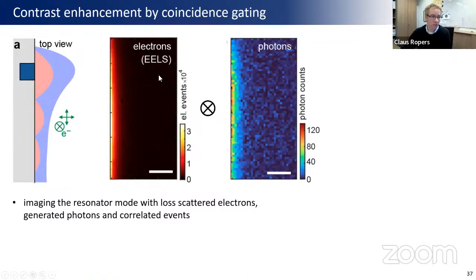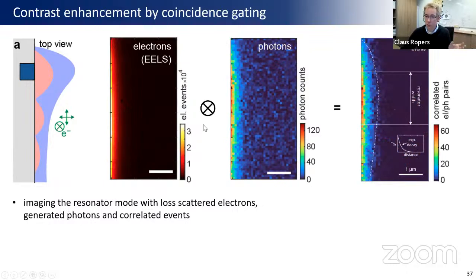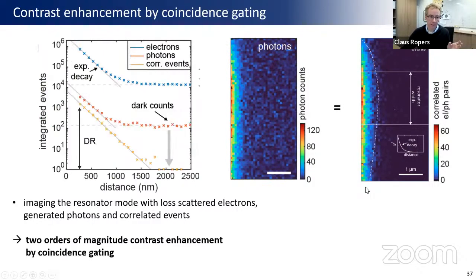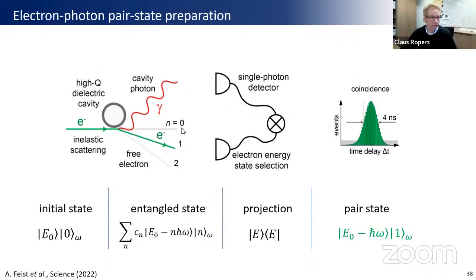So we have electron energy loss distribution, scanning the electron beam in the vicinity of this resonator. We can also plot as a function of this scanning in this vicinity the number of photons collected, but now we can do this in coincidence and basically only look at those scattering events where really one photon has been produced in the cavity. And as a function of distance from this resonator, for example, this may be going into a little bit too much detail, but you can imagine that when you have two observables, the electron loss and the photons produced, you can actually suppress background signals and get higher dynamic range. And what we see here is basically that this coincidence imaging for electron microscopy allows us 2 orders of magnitude signal enhancement. Okay, last slide.